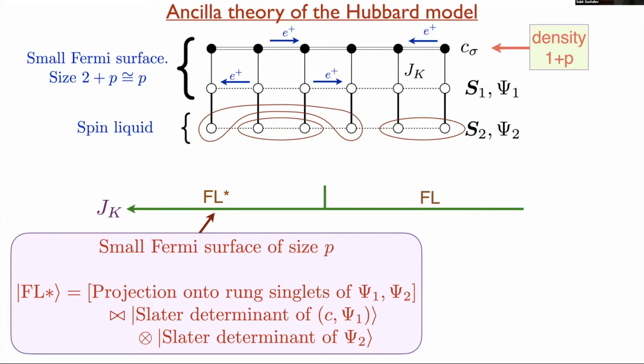from, so basically what you get at the critical point is you have a Fermi surface here, and the hybridization goes to 0. Let's just take the theory of the pseudogap and send the hybridization to 0. That's the main thing. And then you liberate the gauge fields on this second layer. And so you have a Fermi surface of psi 1 also appearing. And then you have a spin liquid of psi 2. And so you can write down a deconfined critical state.